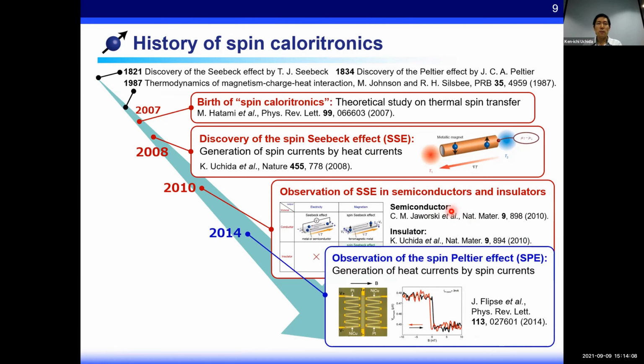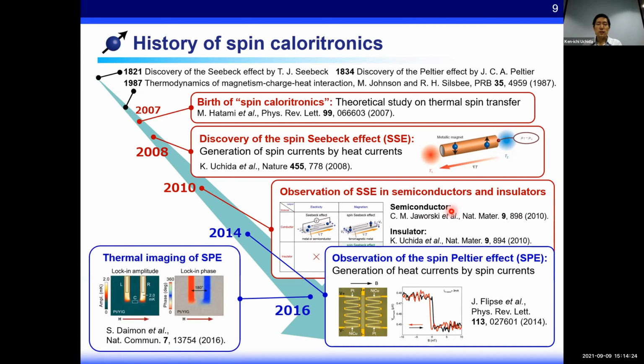Several years later, a spin version of the Peltier effect was also discovered, which was reported by Professor Van Wees' group at Groningen University. This phenomenon is the generation of a heat current as a result of a spin current. In 2016, we established a versatile measurement method for the spin caloritronic phenomena that output heat current, which provides a new direction in this field.